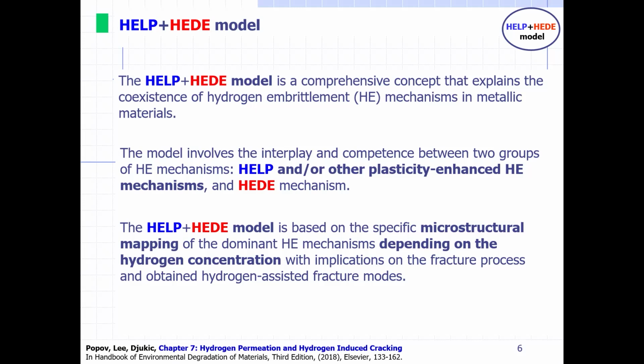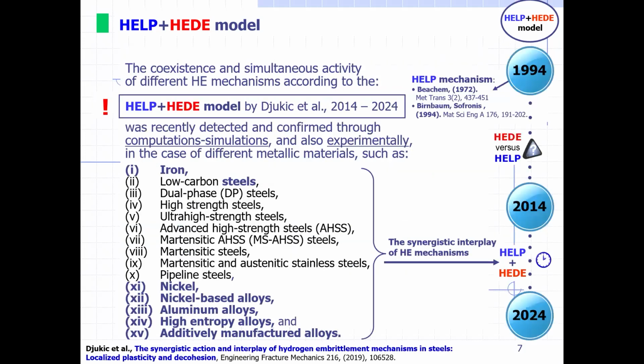So HELP and other plasticity mechanisms together with HEDE are synergistically operative. And this HELP HEDE model is based on very careful microstructural mapping of the dominant hydrogen embrittlement mechanism depending on hydrogen concentration, microstructural characteristics of material, and stress-strain state of the material, in order to reveal the various hydrogen-assisted fracture modes after failure. So, the HELP HEDE model is confirmed in iron, in almost all types of steel,